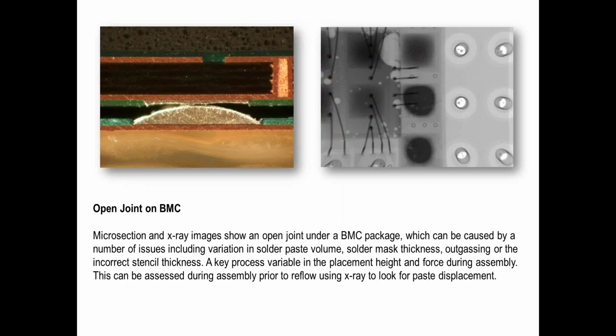Clearly we've got an open intermittent joint on this area array LGA QFN type package, and one of the biggest variables I find on this style of package is that companies don't control their downstop. So when they're placing components onto the printed circuit board, they tend to overplace and consequently displace paste, and then it reflows. Some of it moves away from the pad area, so you haven't got the same sort of volume. So any indication of stray paste or small solder balls away from pad areas are an indication of overplacement pressure 9 times out of 10. This then may lead to open circuit interconnections potentially.